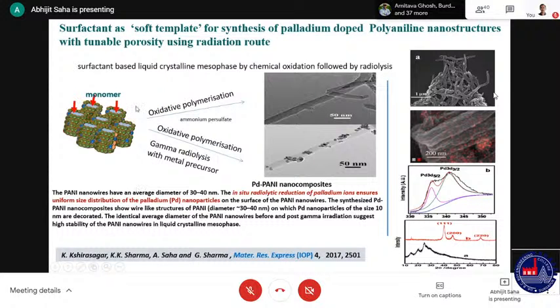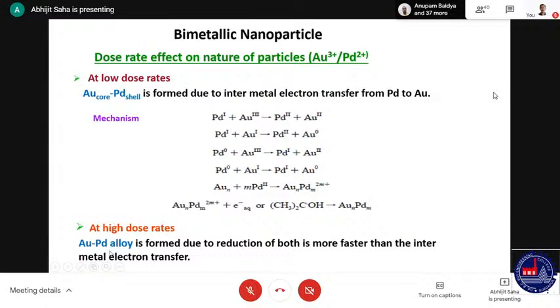But if you go for a high dose rate, then we can have an alloyed structure, not the core-shell structure. This is an alloy, a mixing of the crystalline materials. This alloyed structure is formed because the reduction of both metals is faster than the intermetal electron transfer. When the core-shell structure forms, it is through intermetal electron transfer. But at a high dose rate, the intermetal transfer is slower compared to the direct reduction of gold and palladium, so you get alloyed materials. So whether we get alloyed materials or core-shell structures, it is basically a bimetallic structure. So you can see that using radiation, we can get different types and different sizes of materials.